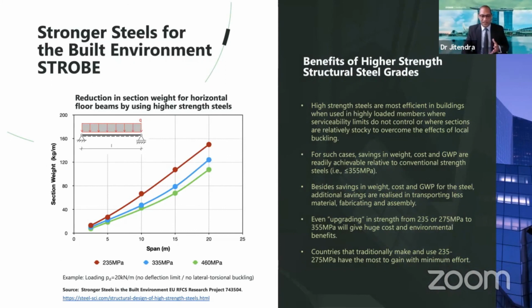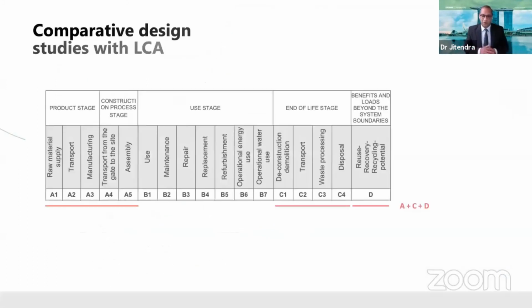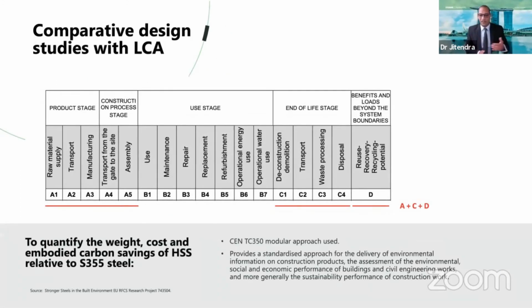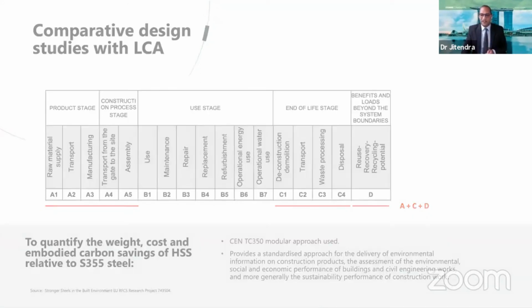And basically, we looked at a number of higher strength steels and the solutions of that from a sections and a hybrid girder point of view. But it again shows here, as you go to 460 higher strength steels, we're able to reduce the weight of the structure and make significant benefits. And this was an example for horizontal floor beams for most buildings. To look at the LCA, we use the CEN/TC 350 approach. That's a standard methodology which is being used in the industry to look at the embodied carbon savings all the way through from raw materials all the way through to end of life and recycling.